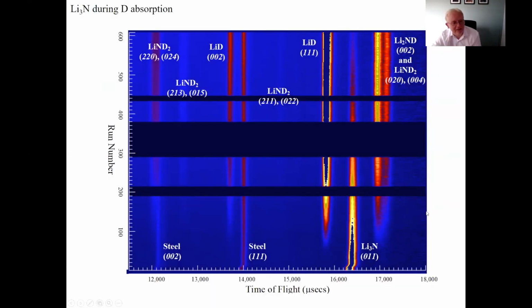And this is a sample Bragg image from lithium nitride being hydrogenated to lithium amide and lithium imide. The big gap in the middle is where the beam went off. This is one of the hazards of doing a neutron experiment, especially if it's a neutron experiment where you can't stop. These sort of thermodynamically favorable processes, once the hydrogen gas goes on, it will continue. And so you just have to collect data.